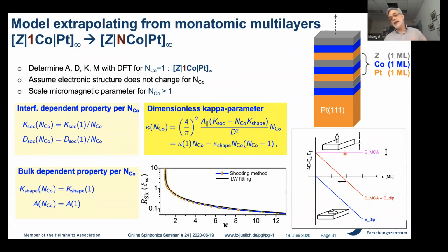And the easy axis of these magnets is typically out of plane. And if you now increase the thickness of the cobalt materials, you have this shape anisotropy as a function of thickness. And there is one point which is called a reorientation transition. That's the thickness where you change from out of plane to in plane. But prior to this point, there is a point where this becomes so small that you are at kappa equal 1 and basically your radius diverges. So prior to coming to this reorientation transition, there is a point where basically your Skyrmion radius explodes.